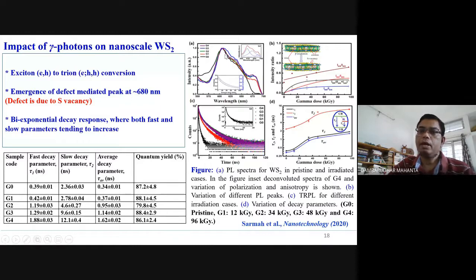Otherwise, it will be very, very symmetric. Then the origin will be only one, that is excitonic luminescence. But in this case, we are seeing that yes, there is a modulation over here, a manifestation in this particular peak. And apart from these 2 peaks, you are getting another peak which is located at around 680 nanometer. And this is because of these defects, what we are saying is due to sulfur vacancies. So these 3 positions are very, very important.